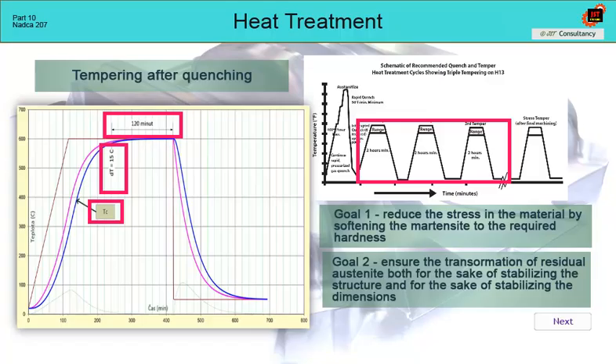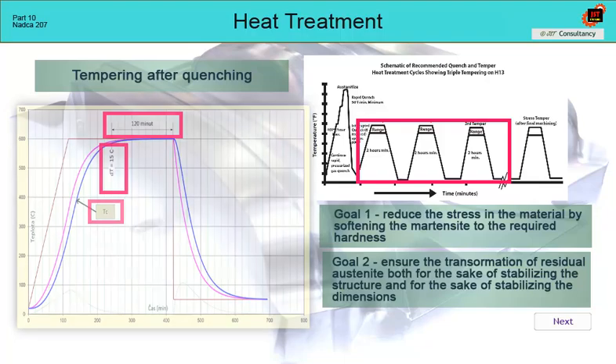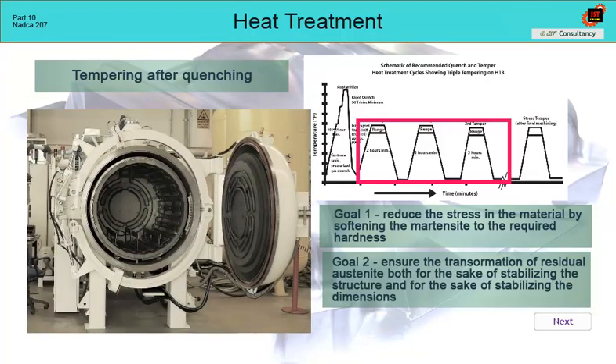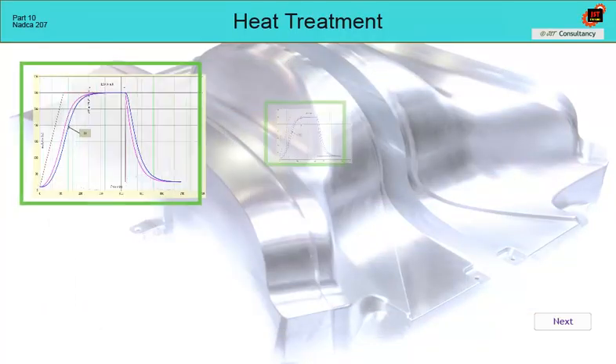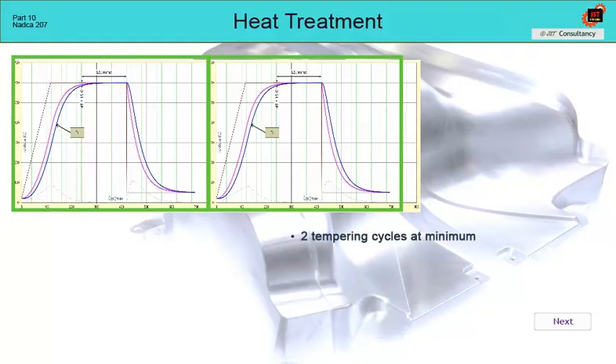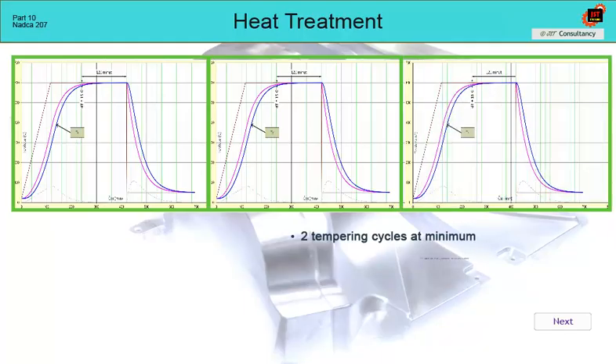The resulting hardness depends not only on temperature, but also on time, and a change in the delta T parameter means a significant impact on the tempering results. Tempering should be carried out under vacuum or under a protective atmosphere. The number of tempering is set at a minimum of 2 tempering cycles. In cases where we require maximum mechanical properties and dimensional stability at the same time, tempering 3 is recommended. The reason is as follows.